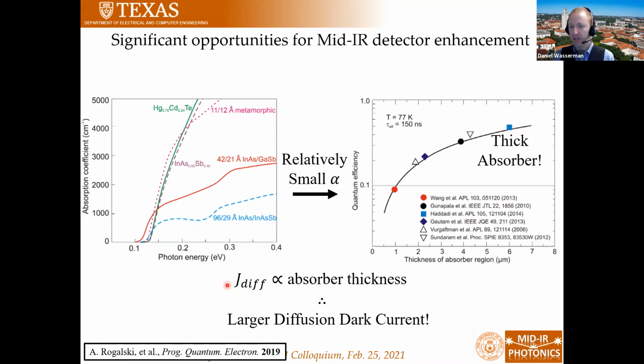But the other reason is that your noise, or essentially your dark current, is proportional to absorber thickness. So the thicker you make your device, the more dark current and the more noise you're going to have. And unfortunately, the way that we measure the quality of a detector is essentially two parts. In the numerator, we have the efficiency of collection, and in the denominator, we have a noise term, or the noise equivalent power. That gives us the detectivity. So basically you can make it thicker, but you're not adding anything to the numerator, and you're making the denominator much larger. So your figure of merit's going to go down.